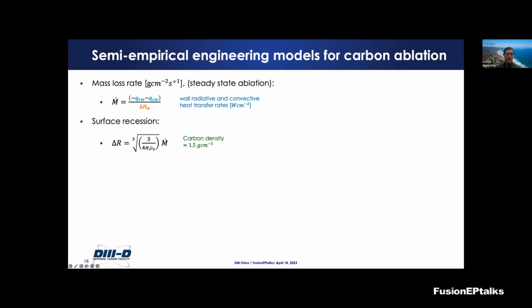I mentioned these semi-empirical engineering models for carbon ablation, and typically, if you want to get the mass loss rate, you need to know the heat fluxes, and you need to know the heat of ablation coefficients. We can measure those Q values from the experiments, but how do we get the heat of ablation?